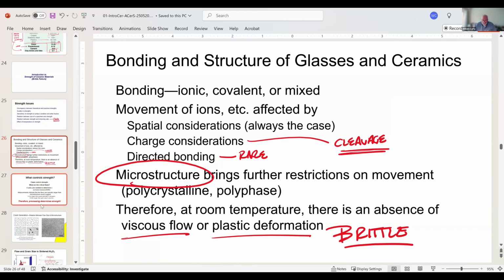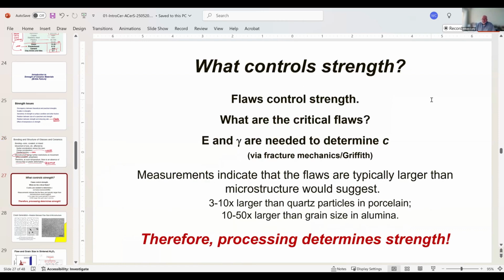Okay, so what controls the strength? Flaws. It's actually that simple. Okay, flaws control the strength. What's a critical flaw? Well, a critical flaw is the flaw that dictates the strength. So if I have a specimen, okay, when I was a student, not really understanding this very well, I thought, well, can I calculate what my flaw size should be? And the thing is that your flaw size then is dictated by your strength. So the strength then is a function of 1 over the size of the flaw. So as my flaw size increases, my strength goes down. C goes up, strength goes down.